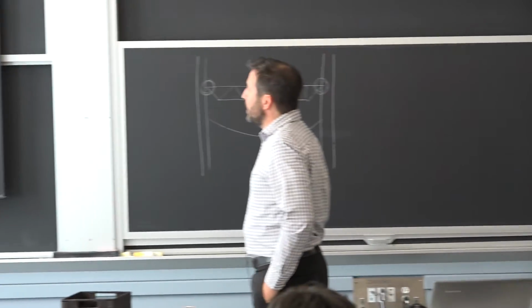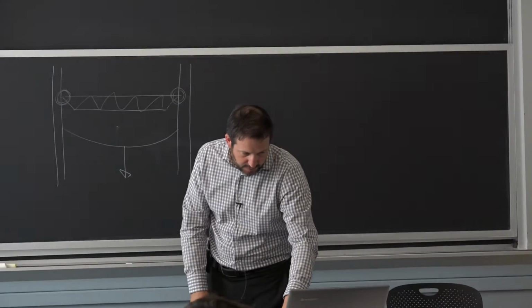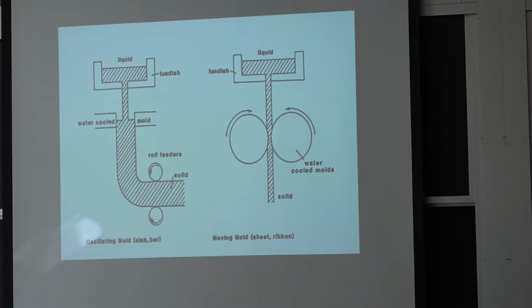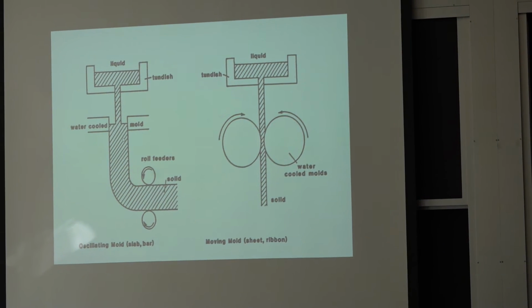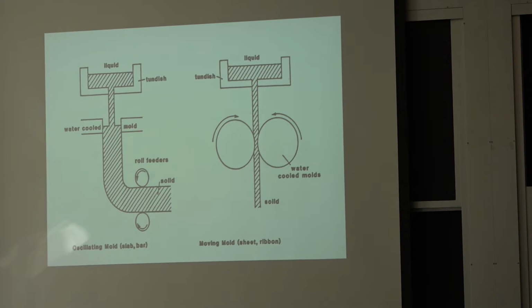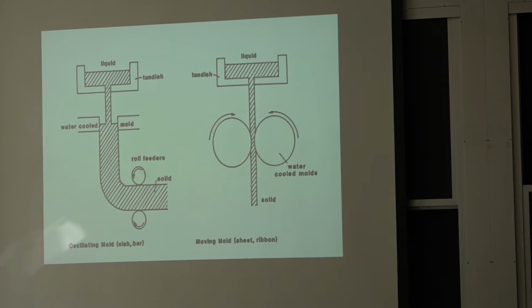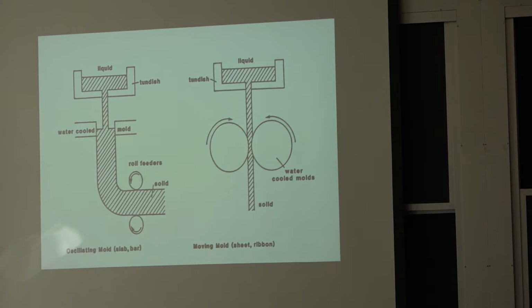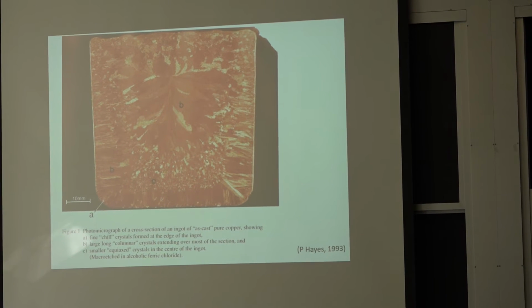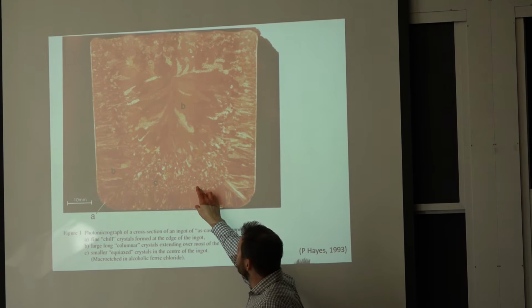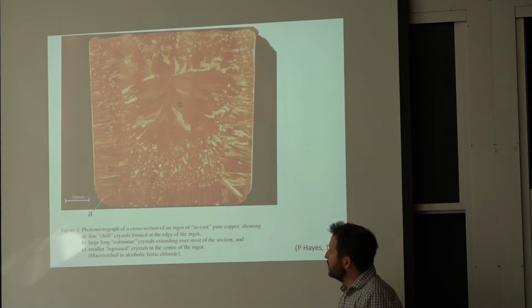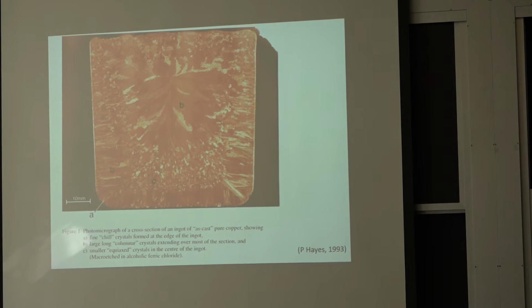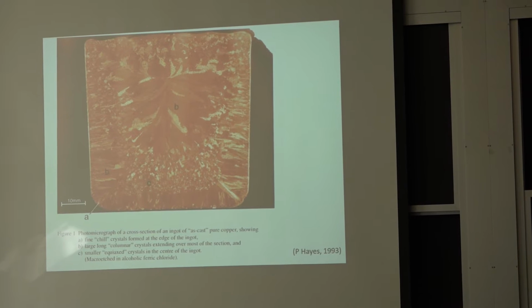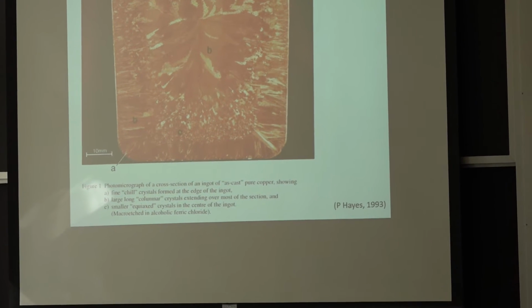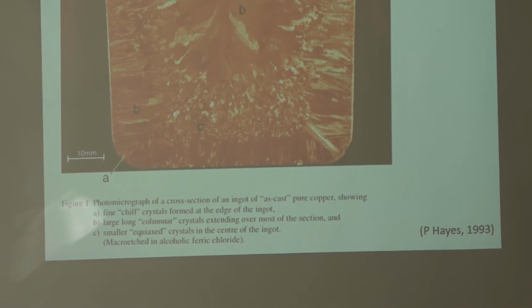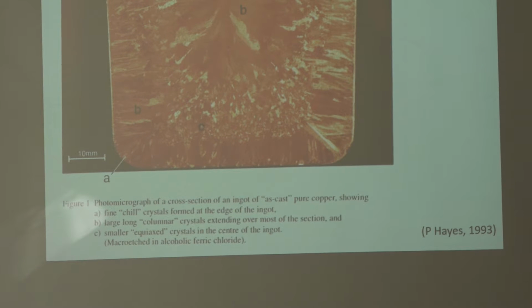And what it is, you start vertical into this cavity, so I have a schematic of it. So you have your liquid that gets into a mold vertically, because otherwise you can't do it as a continuous process. And this mold gets cooled, and so you start to solidify on the outside and then get to the center. So what happens on a big part like this, an ingot, is you see this chill zone. You have a very different microstructure on the surface, and as you get to the center, it goes through different stages. Essentially, your cooling rate's going down. And then you also have an effect where a lot of the alloying addition that you put in stays with the liquid. It's thermodynamic. They don't really like the solid as much. There's not as much room for them. So what we have is what we call chemical segregation.